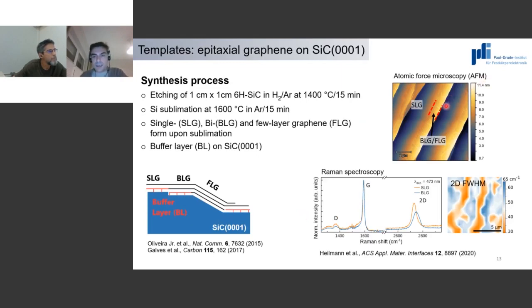What we usually see, since epitaxial graphene nucleation starts at the step edges, is that you usually end up with some bilayer graphene or few layer graphene close to step edges, while the terraces are covered in single layer graphene. And in addition to that, we always have, making the interface between silicon carbide and the graphene layers, which are decoupled from the substrate,